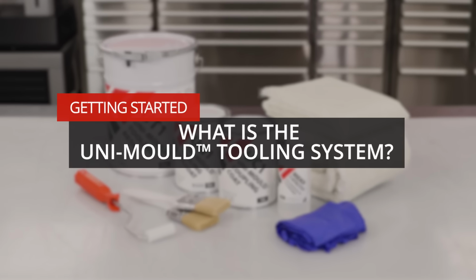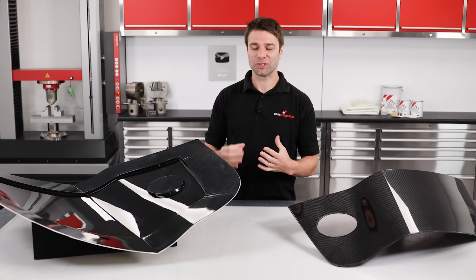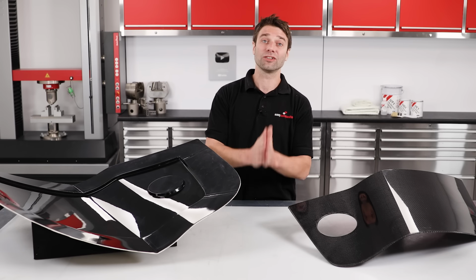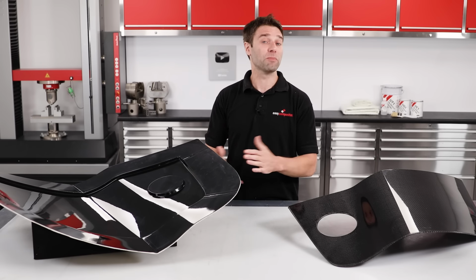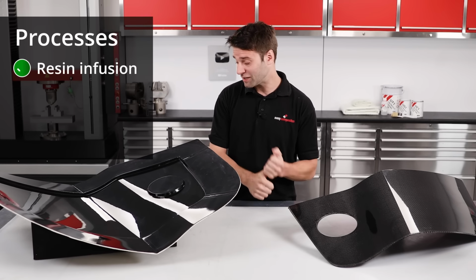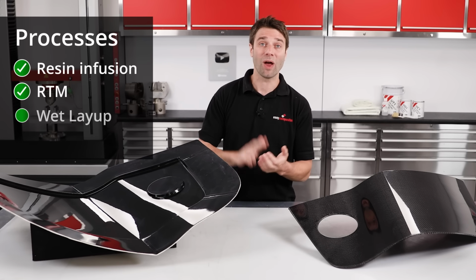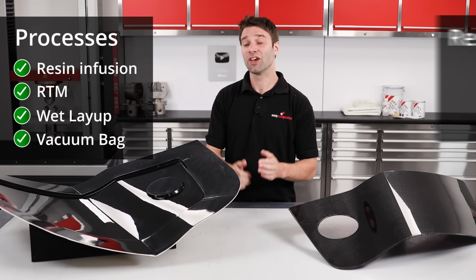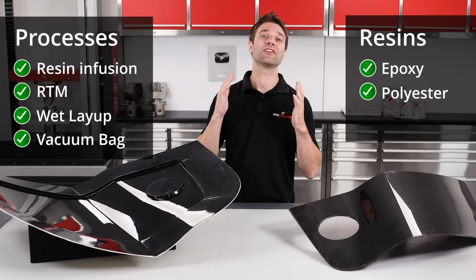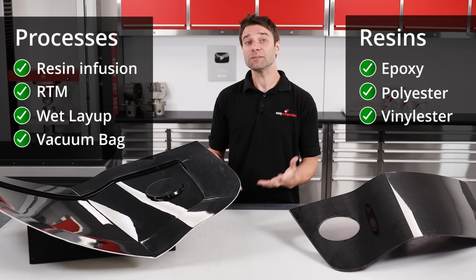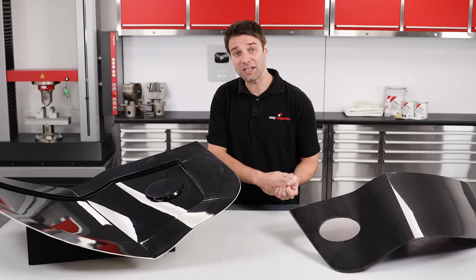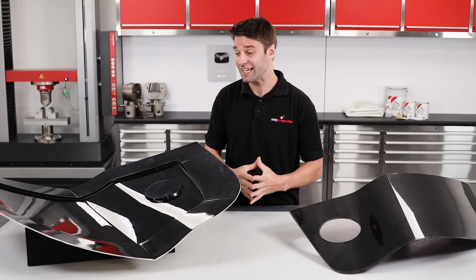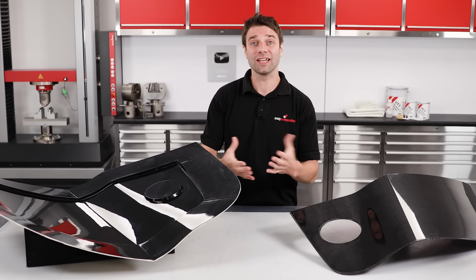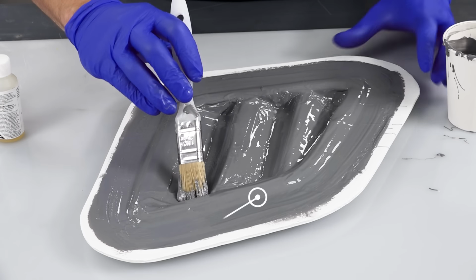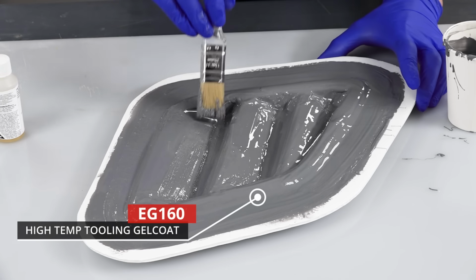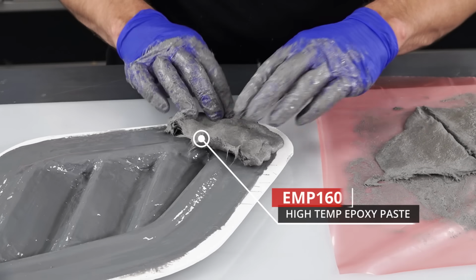Uni-Mould is a highly versatile mold making solution that produces accurate, durable and cost-effective molds that can be used for most composite processes, including resin infusion, RTM, wet layup and vacuum bag processing of epoxy, polyester and vinylester resin systems. This makes it ideal for ambient and medium temperature cures up to 90 degrees C, so it is suitable for nearly all applications, with the one exception of pre-preg moulding, where a high temperature epoxy system is going to be